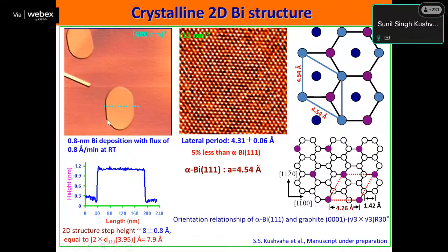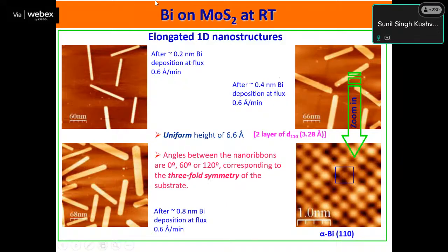For example, even here where there is no growth, just locally we can see this is a 200 nanometer size structure, and from the top of this one we are able to see it is again showing the bismuth 111 structure. Here we grew some nanorods or nanoplatelet structures, and after zooming again we are able to see this is the bismuth 110 structure. Even inside this one we are able to see exactly the crystal lattice formed for that bismuth 110 structure. So this is some of the examples.